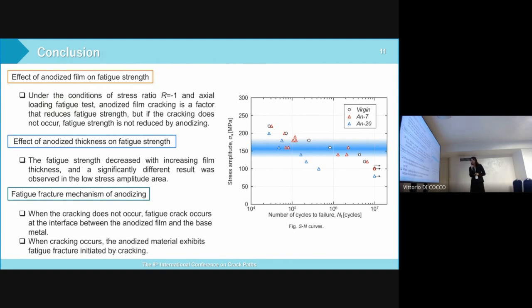Finally, the fatigue fracture mechanism of anodizing. When the cracking does not occur, fatigue cracks occur at the interface between the anodized film and the base metal. When cracking occurred, the anodized material exhibited fatigue fracture initiated by cracking.